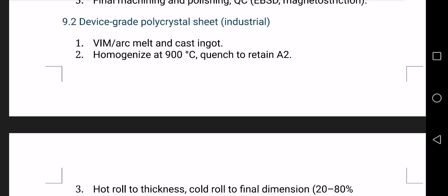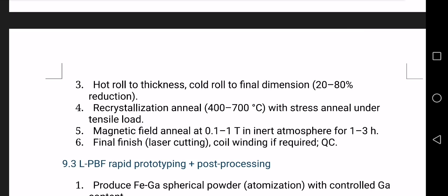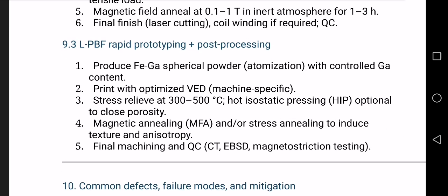Device grade polycrystal sheet, industrial, and its steps are: melt and cast ingot. Second, homogenize at 900 degrees Celsius, quench. Number 3, you have to roll, hot roll and cold roll. Number 4, recrystallization with stress anneal. Number 5, magnetic field anneal, 0.1 to 1 Tesla. Final cutting and QC.